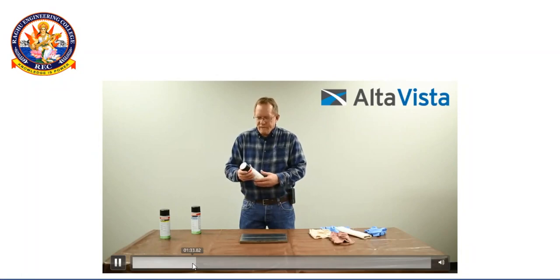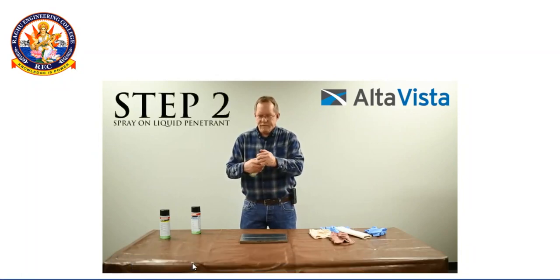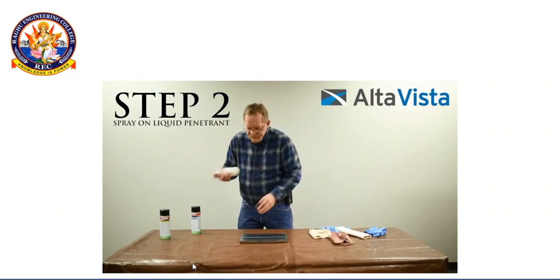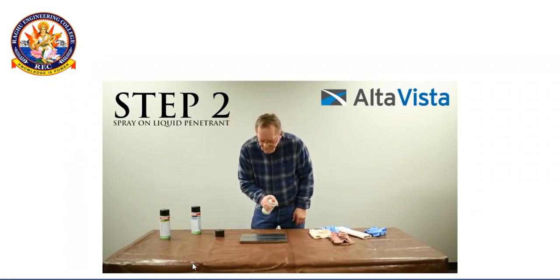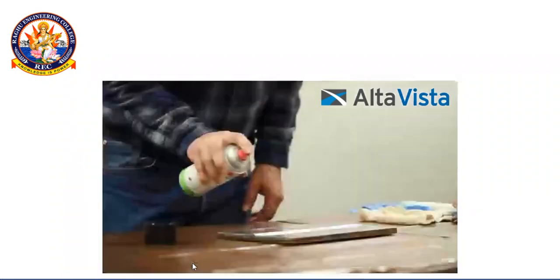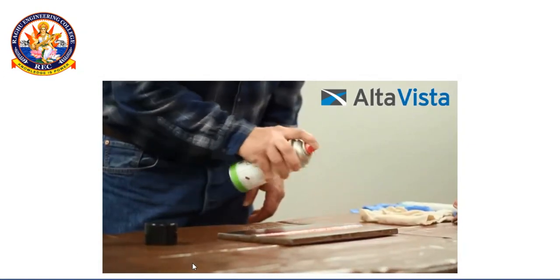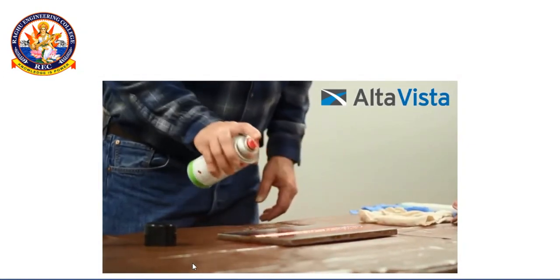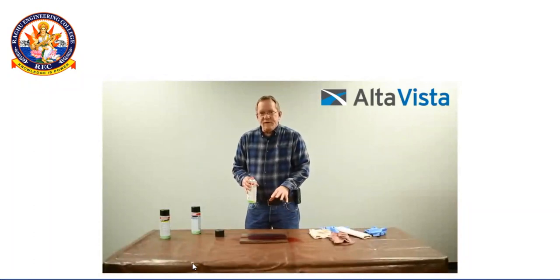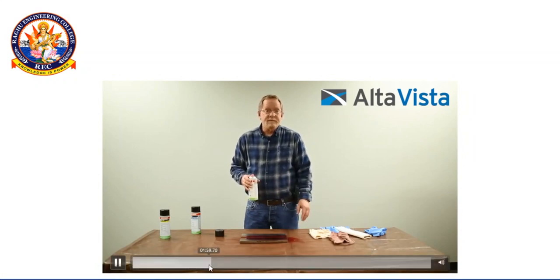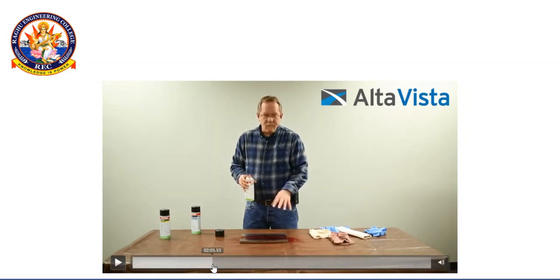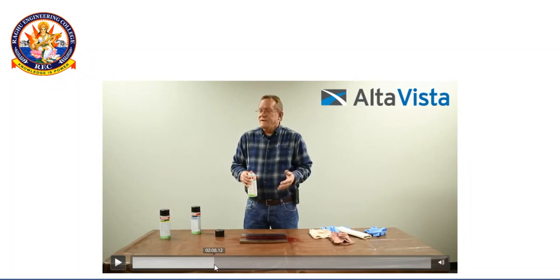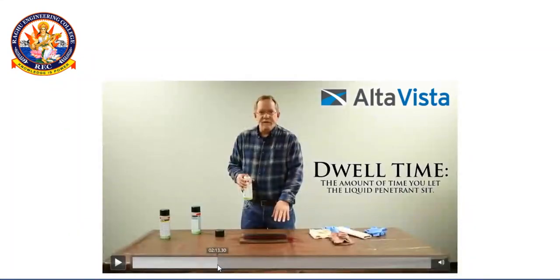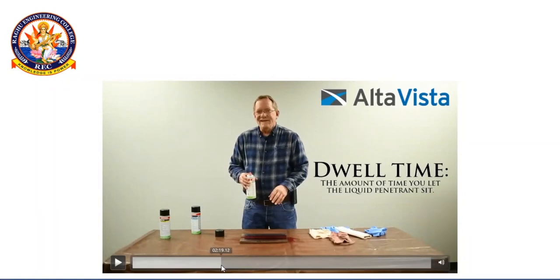They properly cleaned all the surface. There is no spray of the liquid penetrant yet. It should be in a fluorescent color. He is just spraying very slightly on the surface of the weld joint. Generally 10 to 15 minutes we allow that material to penetrate into the flaw, and that is called the dwell time.